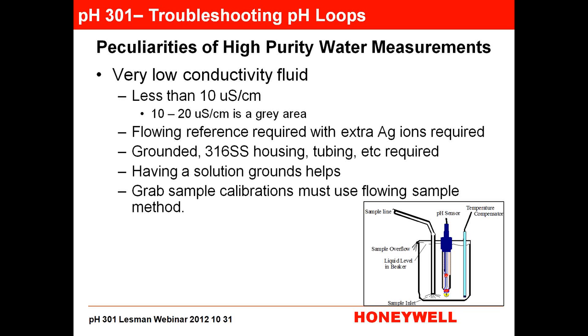When you open that sample to the atmosphere, what happens is carbon dioxide in the atmosphere dissolves inside and it lowers the pH, makes it more acidic, and it raises the conductivity. And it happens really fast. And if you're standing over that beaker and you're breathing out into it, it will happen even quicker because we breathe in oxygen, we take oxygen out of the air, and we expel carbon dioxide out of our lungs, which is why everything is more acidic when you've got a room full of salesmen, because we're all full of hot air. So you have to do